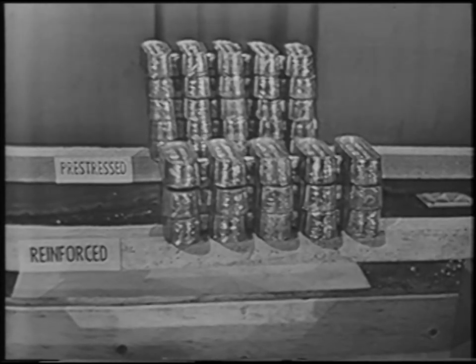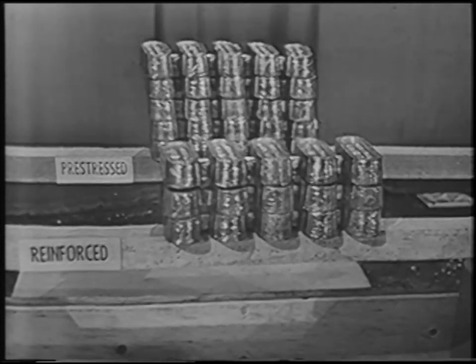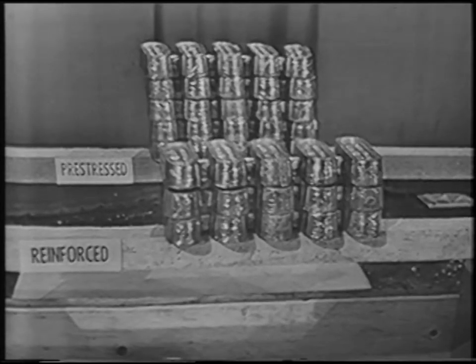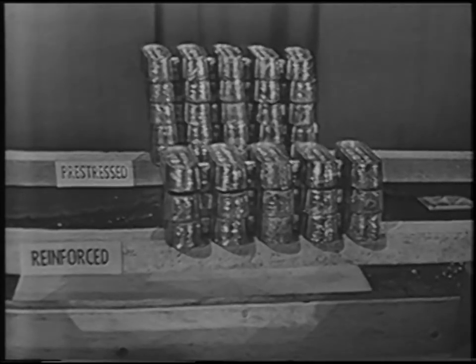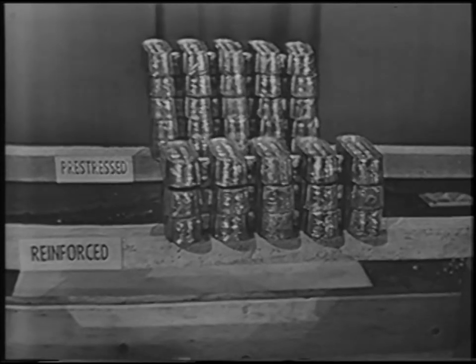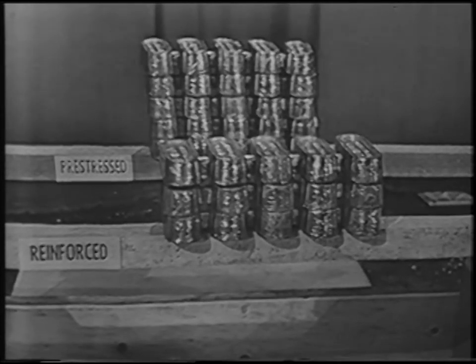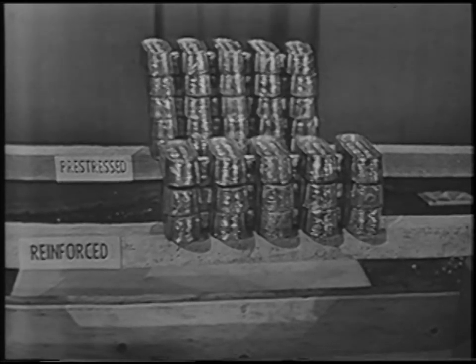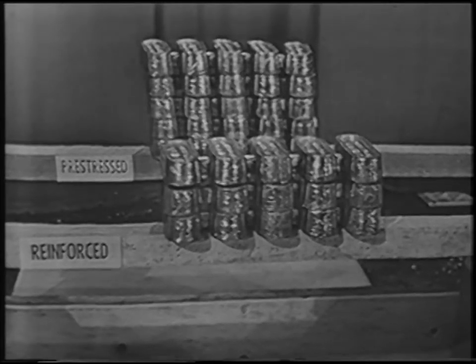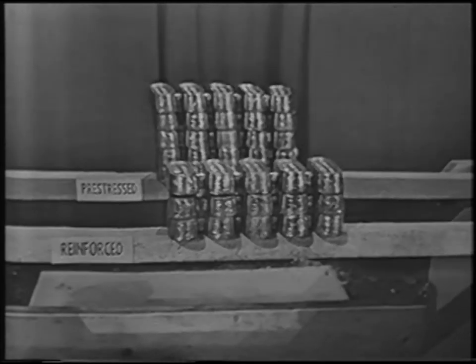Three loads, about 100 pounds, being placed on the reinforced beam, 166 pounds on the pre-stressed beam. Yet the pre-stressed beam deflects less than the reinforced concrete beam. A wonderful demonstration of its capacity in this particular application. Pre-stressing reduces the bulk and weight of structural members. This method uses about half as much concrete and saves just about 75% of the steel.